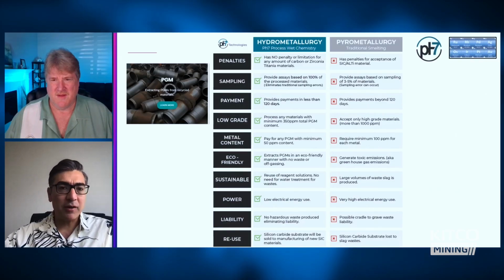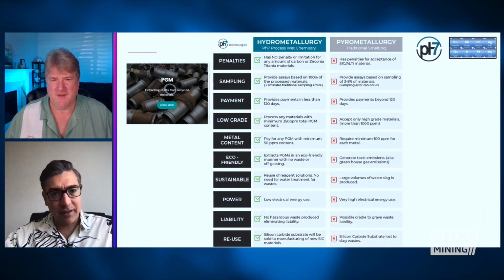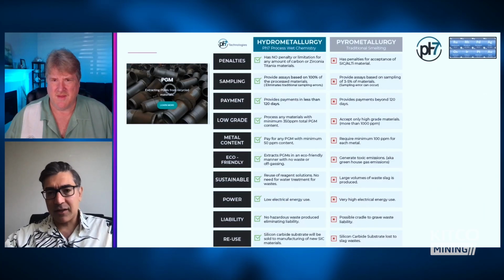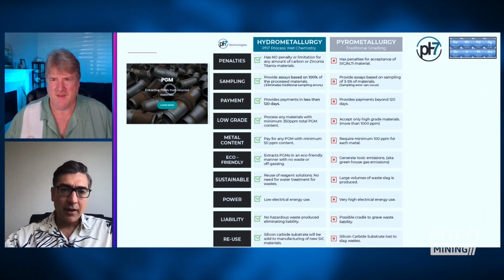So I see PH7's process as complementary to pyrometallurgical processes. There are some materials that we cannot process, the materials that cannot be formed into a powder. It's impossible for us to process them because we cannot pump them, we cannot run them as a slurry through our leaching reactions. But the materials that are problematic for smelting furnaces can be easily processed through our processing plants. We don't have any penalty for high carbon content. We are not really concerned about carbon content in the materials. No concern with zirconia and titanium, iron content, or any other elements that are a concern for pyrometallurgical methods today.